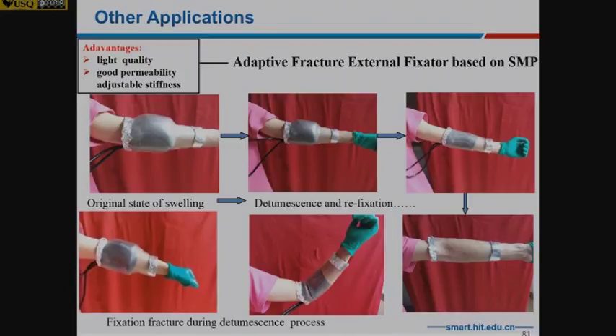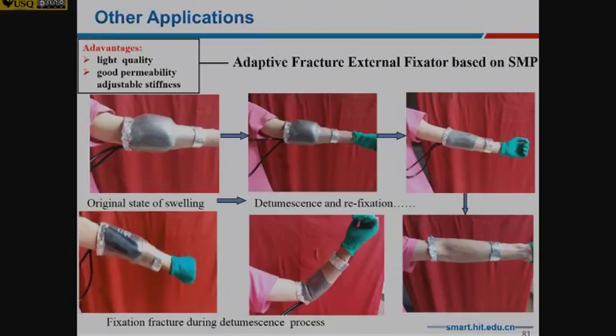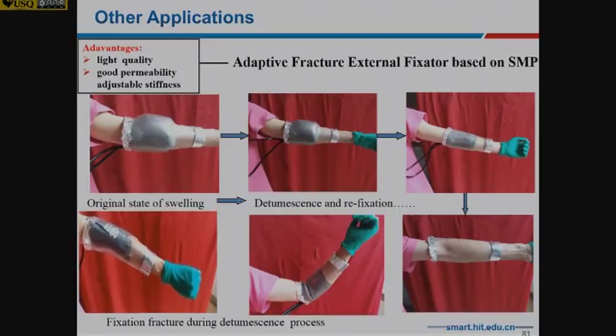So this is another one we call the adaptive fracture external fixator based on SMP. When you have a bone broken, there will be the original state with swelling, and when detumescence comes, the swelling is reduced. So we use shape memory polymer that can fit this. If you're using plaster, normally the plaster cannot change in shape. But with this one, you can change in shape. And also for the joint, you can move to exercise, which plaster cannot do.